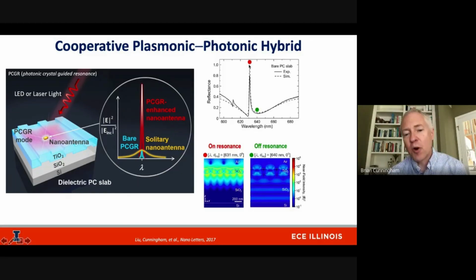If we happen to go off the resonance, to a slightly different wavelength, it's like the photonic crystal doesn't exist, and it's just like a regular piece of silicon or a regular piece of glass where electric field intensity is low. So the thing that we do that's like our electromagnetics trick, it's very simple actually, is that we design a photonic crystal to have a resonance at a certain part of the spectrum, here for example around 633 nanometers.